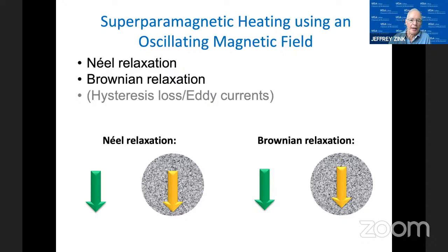There are two mechanisms that can operate, I should say, in the presence of an oscillating magnetic field. They're called Néel relaxation and Brownian relaxation. So this is how the heat is generated. How does this occur? In the case of Néel relaxation, as the alternating magnetic field operates, that's the green arrow on the far left, the electron spins in the domain follow that field. And under the high frequency alternating fields we're using, a hysteresis develops, and that generates heat inside the particle. So heat from the electron motion is what's called Néel relaxation. That's one of the two mechanisms.